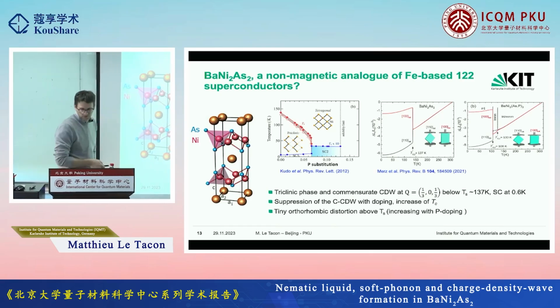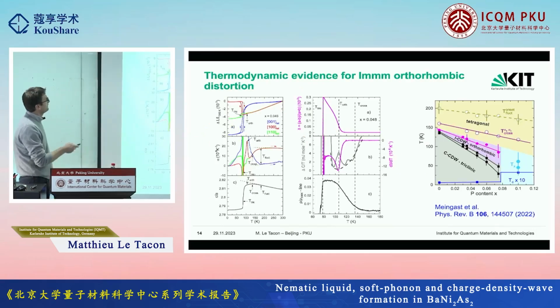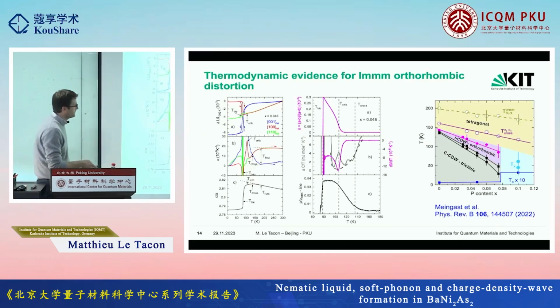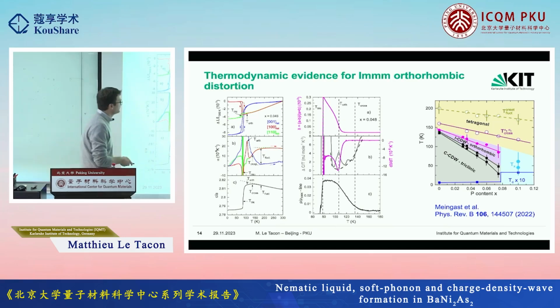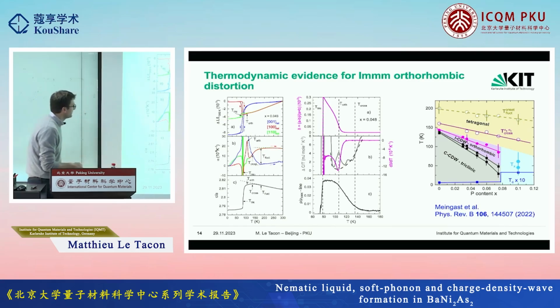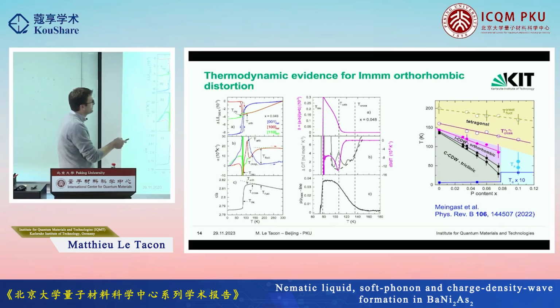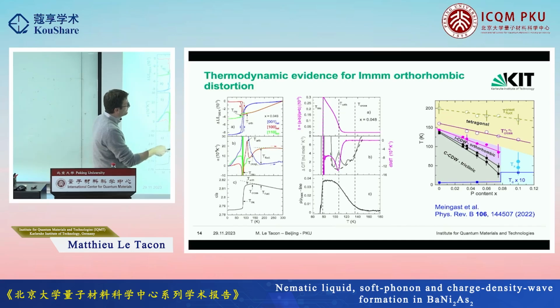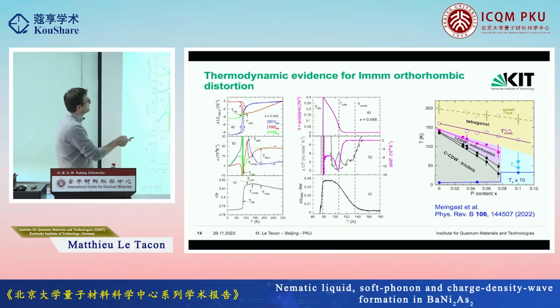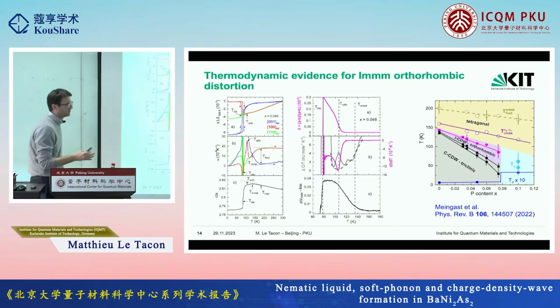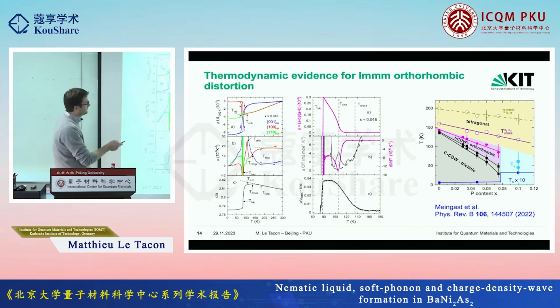Before I show you what I did myself, I just want to point out that Christoph published last year a very nice and complete thermodynamic study of the doping dependence, proposing this phase diagram here. I'm not going to enter the details, but basically you see all those phase transitions. If you look at the orthorhombicity in the doped compound, where it develops a bit more than in the parent compound, you can see the type of distortion. Just to give you an order of magnitude, it's about 10 times smaller than the distortion that you see in the iron-based superconductors. So it's really not big, but it's measurable, and it's quite clear that you see this difference between a and b.